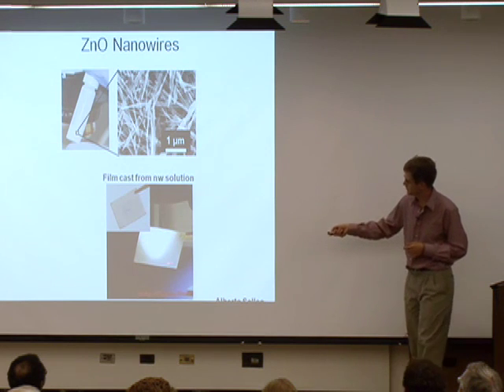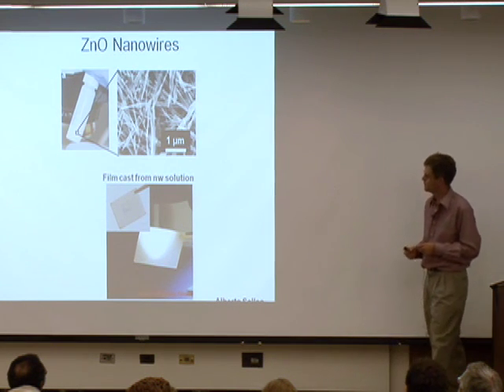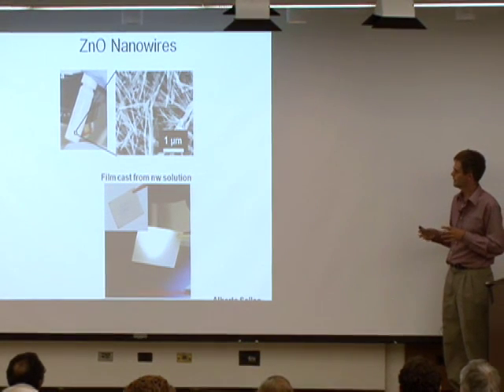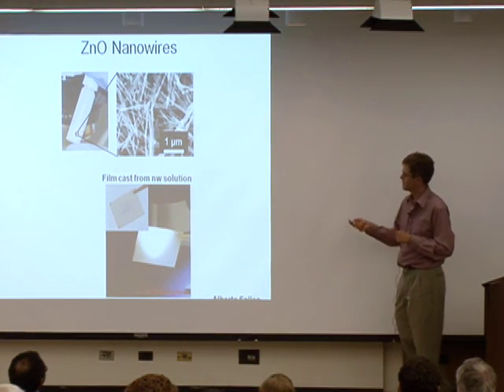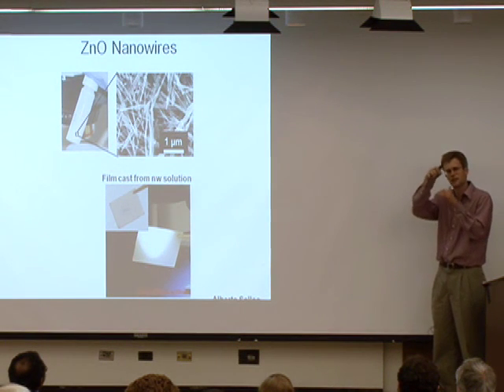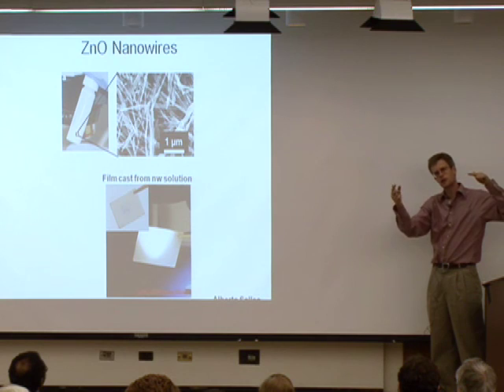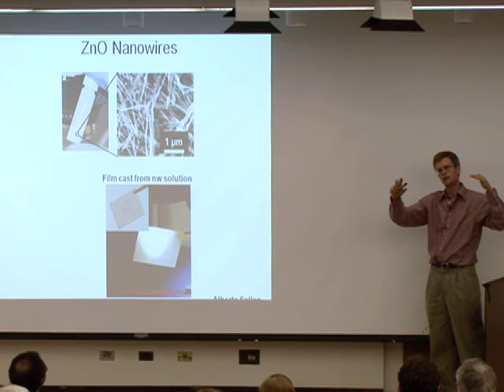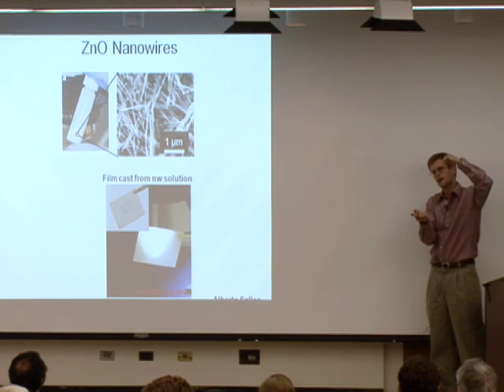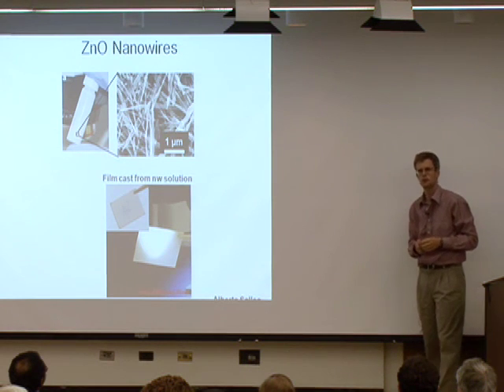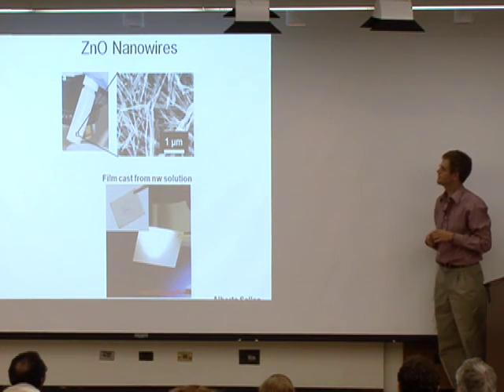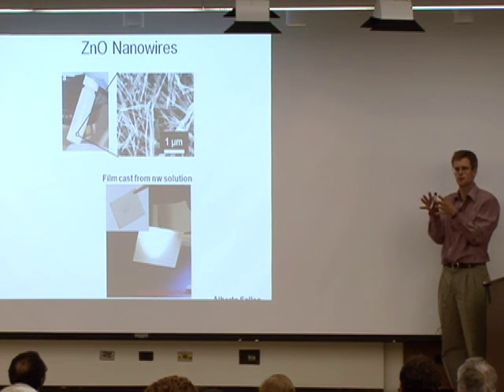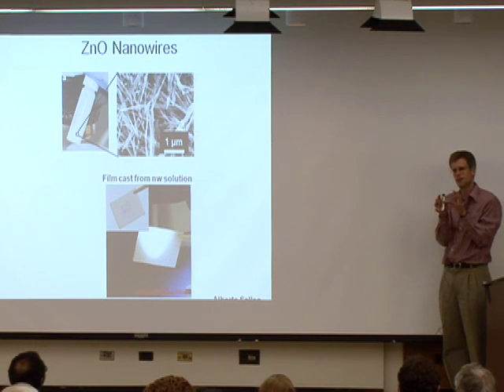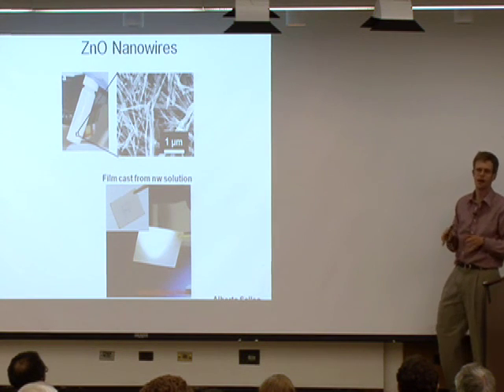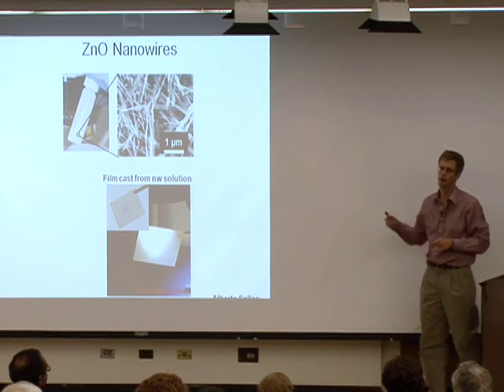What Alberto finds is that these films are milky, and that's because they scatter the light. And while that may seem bad, it could actually be very good for a solar cell because you like to scatter light into the plane and have it travel horizontally through the solar cell because then it will almost certainly be absorbed, as opposed to when it goes through vertically and it only has a short distance in the film to be absorbed. It's also intriguing to think about combining zinc oxide with silver and carbon nanotubes because they each have their own advantages. So it might be that a hybrid will give us the optimal electrode.